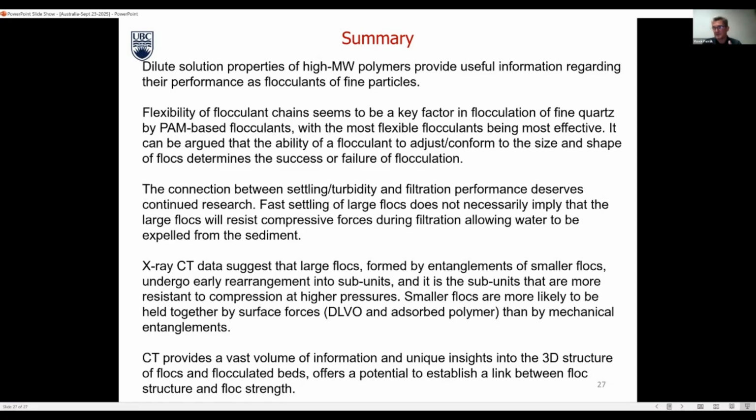The compromise here is the time it takes to collect the data and the resolution, because it's small voxel sizes on the order of 1, 2, 3 microns, and there are now even higher resolution types. It will take days to collect the same volume of data as it takes at a voxel size of about 7 microns, which is some of the dental scanners that we used in our work. But anyway, it's a very interesting technique, very promising, and we found it a lot of fun.